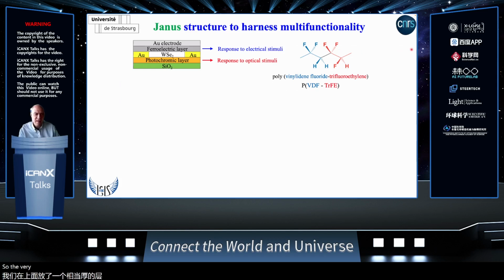The ferroelectric layer placed on the top will act as a gate insulator layer, and we will change the surface potential of the interface with the semiconductor by controlling the accumulation and depletion state of the charges in the device. In this way, we also take advantage of the fact that information can be stored in a non-volatile fashion by exploiting the unique properties of the ferroelectric layer.